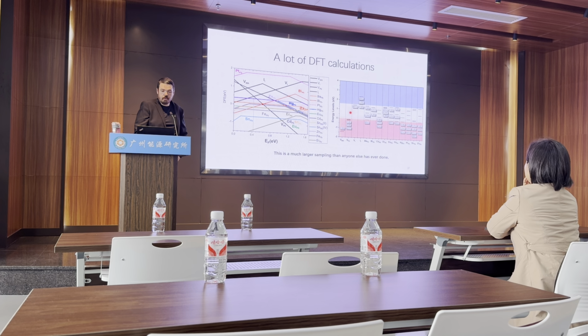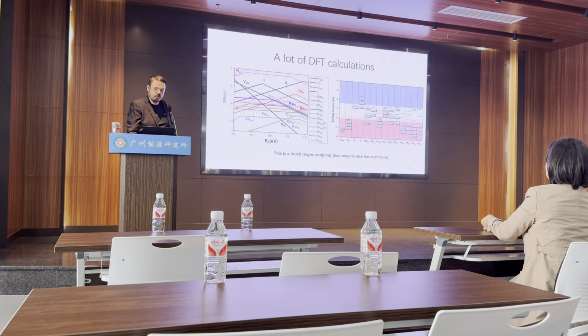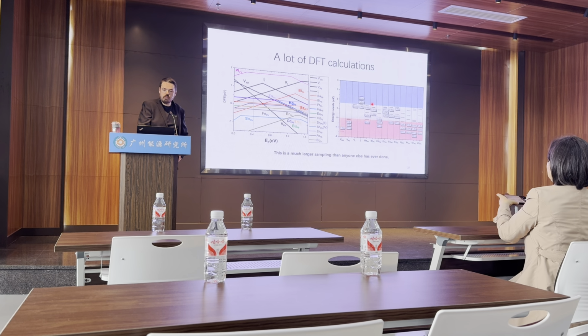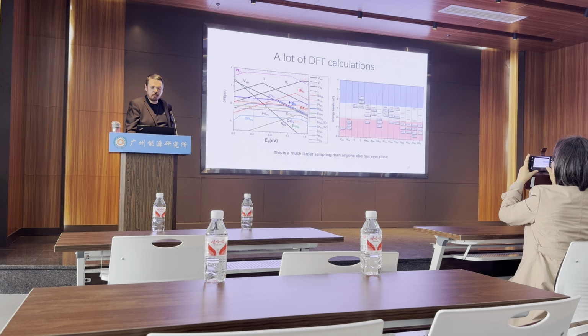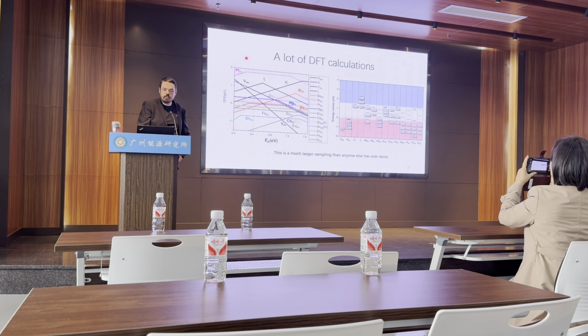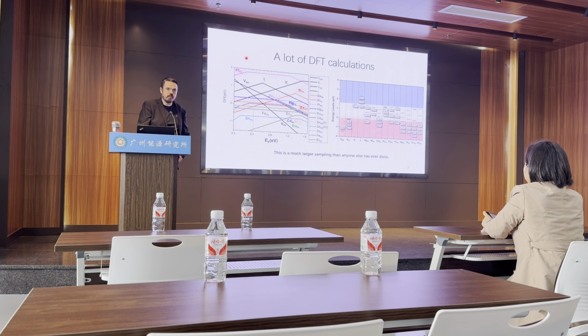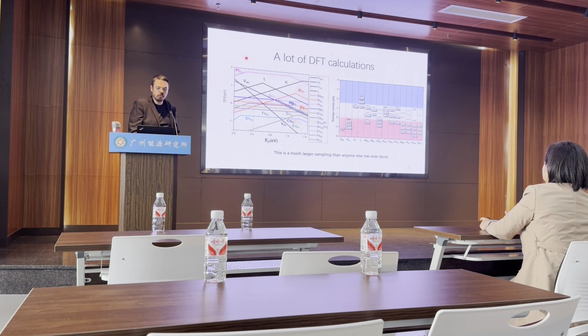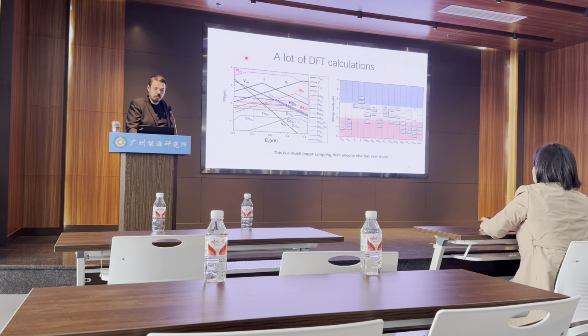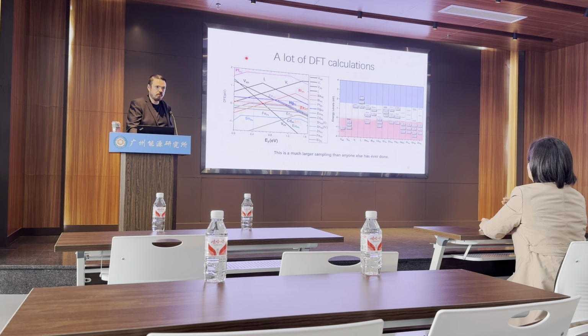Then we did a lot of calculations like the defect formation energies, and then the defect transition energies. So we did a lot. This was a whole bunch of work. The main thing to say here is that no one else has ever done such a large sampling. No one has ever done so many metals at the same time. So that's the cool thing about this section. But the main result was not this. Even though this took a lot of time, this was not the main result.